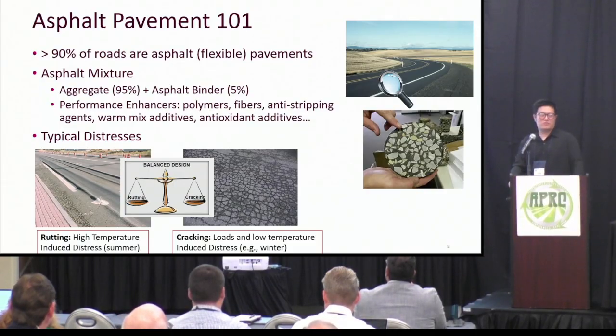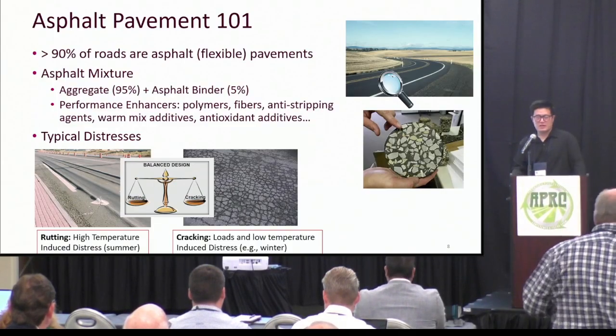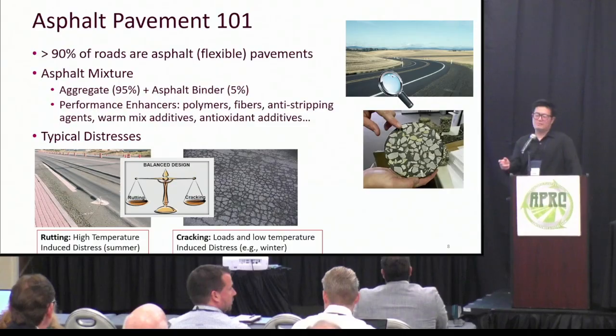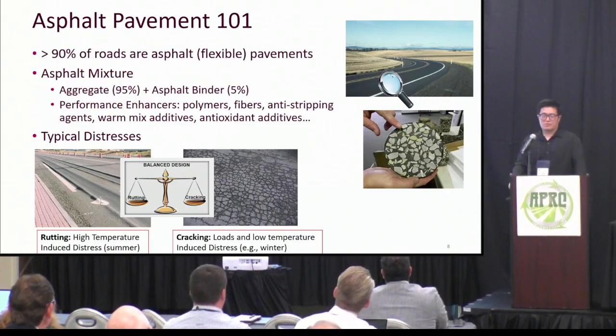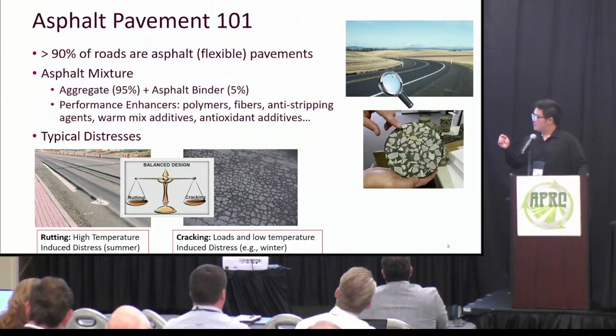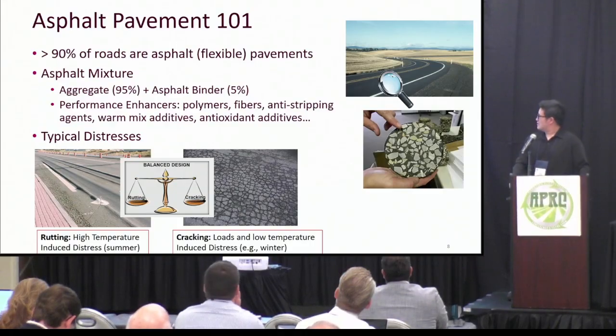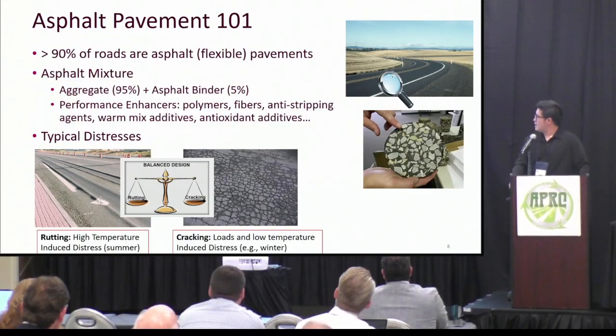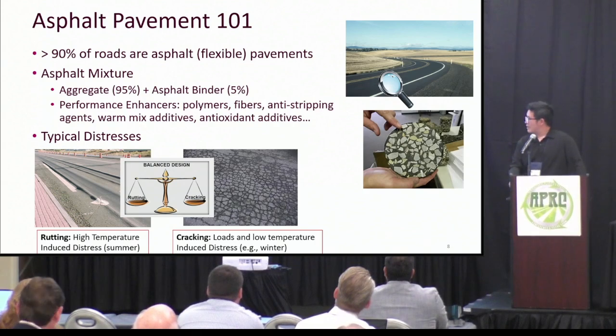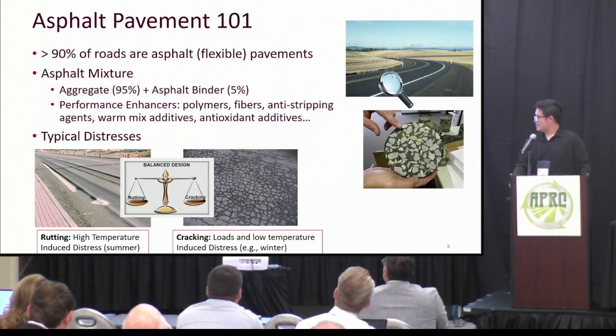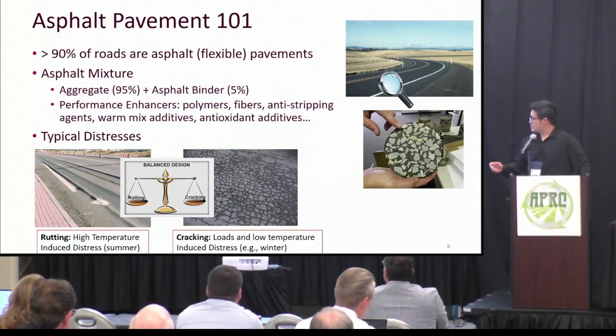To extend or enhance the performance of the asphalt mixture, we have some performance enhancers, for example, polymers such as SBS polymer or SBR polymer. So maybe plastic can be one of the polymers to enhance performance of the asphalt mixture. And then we also have fibers and anti-stripping agents or some additives such as warm mix additives and antioxidant additives. And in asphalt pavement, there are two main distresses. The first one we call rutting or permanent deformation. This rutting distress is high temperature induced distress. So during the summertime, the asphalt is very soft, and in that time the rutting happens. And the other one we call cracking, which is low temperature induced distress.